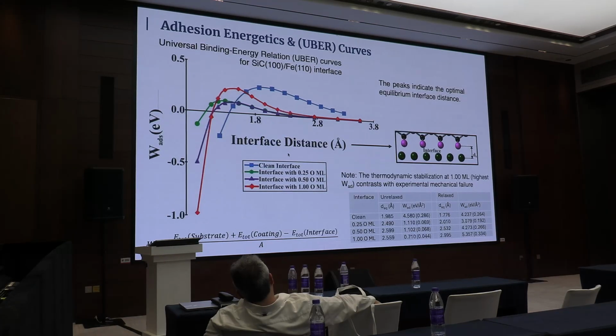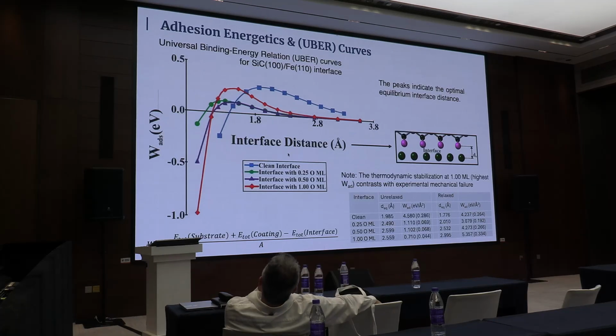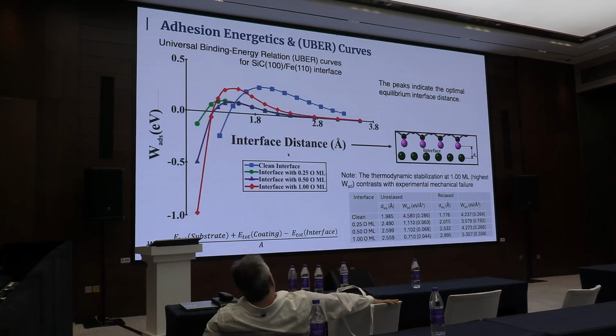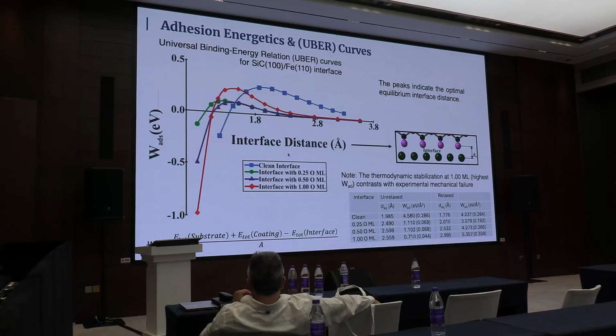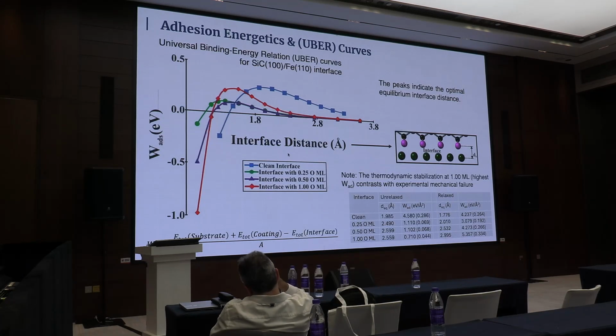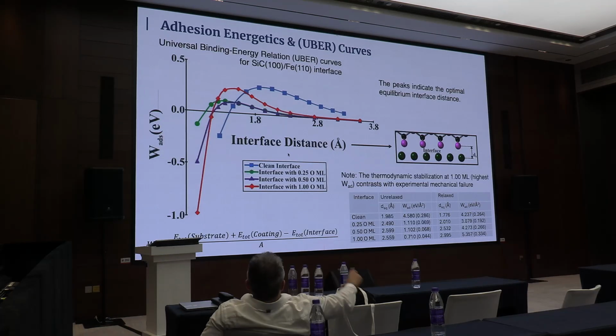So these are the UBER curves, and we also compute the adhesion energy that comes from this. The adhesion energy is the peak of this curve, the maximum value, and it shows us what happens when the surface is pulled up. What we do to compute this is start with just the interface without oxygen, and we did the same for all the surfaces. We start to force the system to go up and separate the substrate from the interface, increasing this distance point by point, and compute the energy.